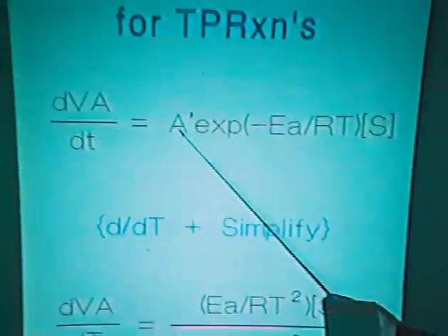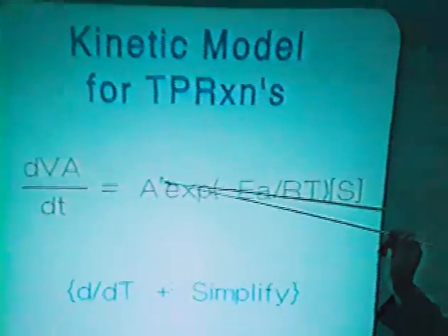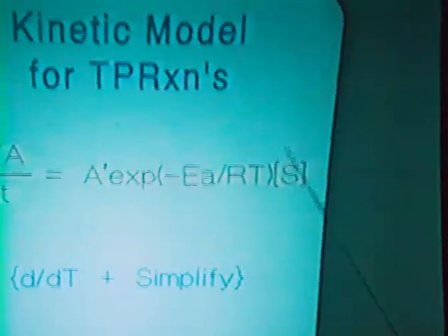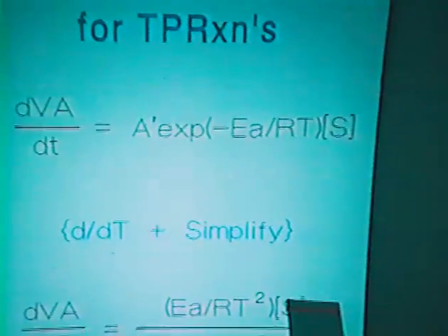The way the reaction was run was that ethylene and oxygen were run in such a great excess that they were essentially constant through the reaction. So we take those concentrations and stick them in our pre-exponential factor. We needed to assume that whatever that thing was on the surface, it reacted under first order kinetics to form vinyl acetate. With those assumptions made, we can use a very simple empirical kinetic rate law to define the reaction.